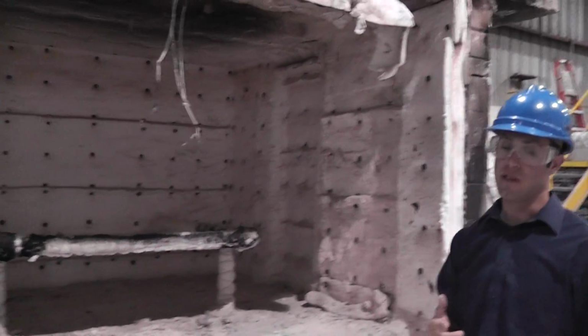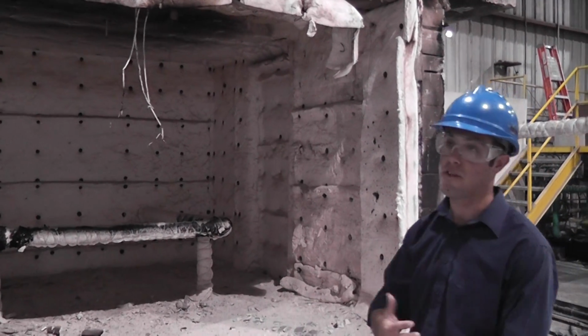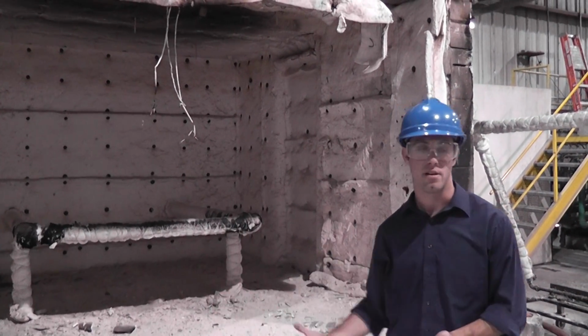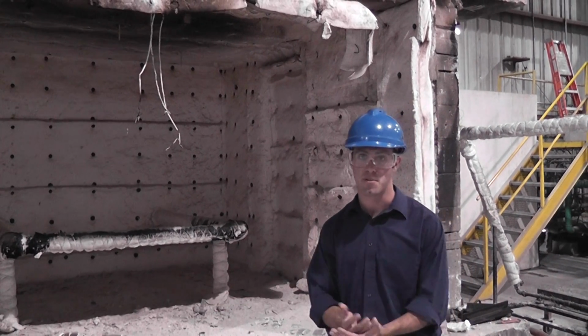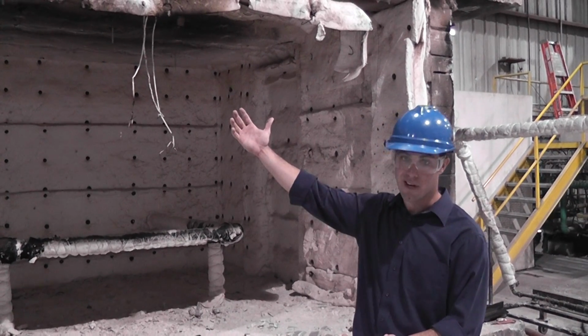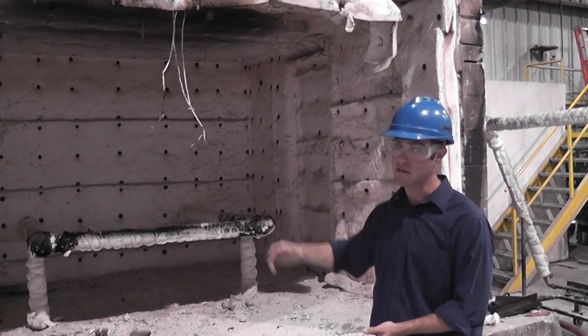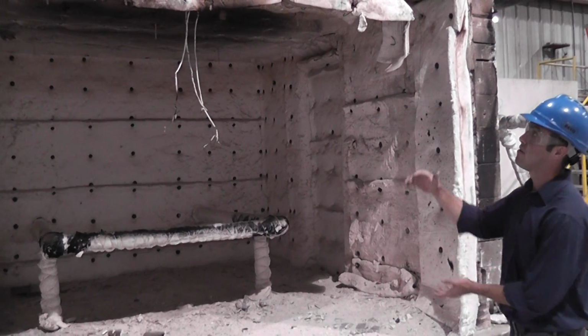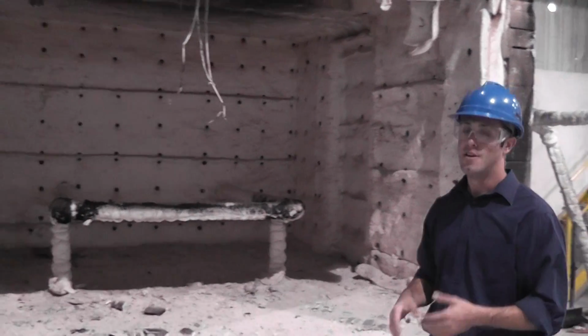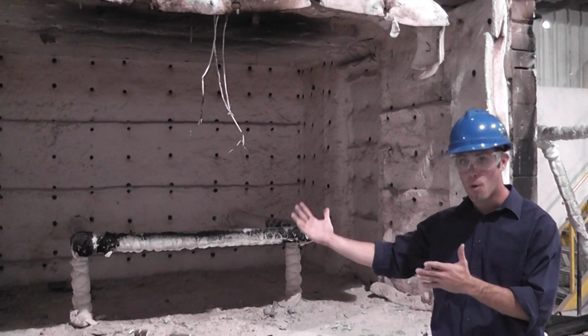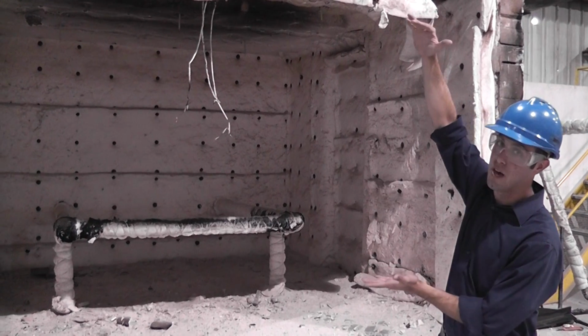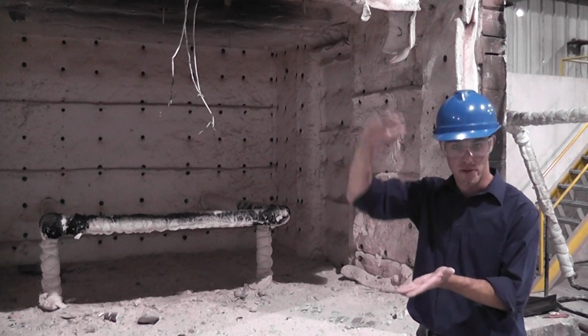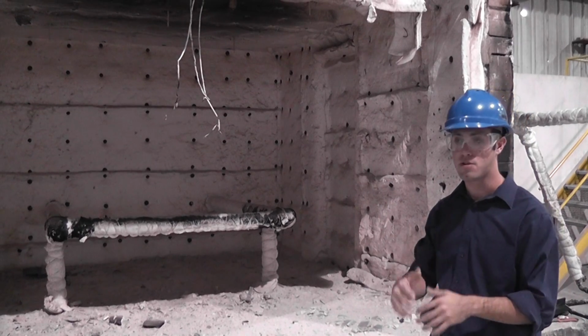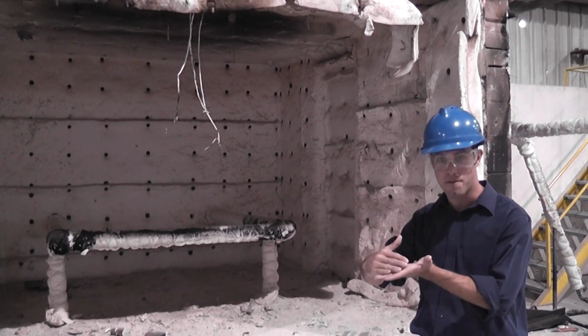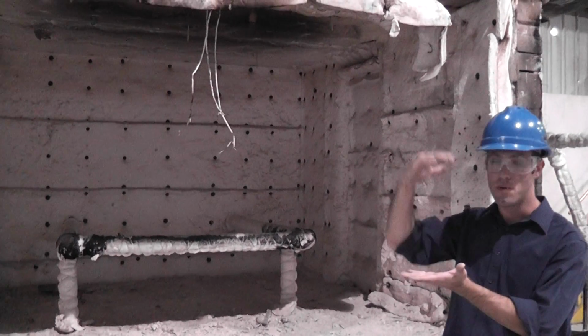So that's 5 minutes into the test. That condition continues for another 25 minutes in the test, and every 5 minutes we up the gas flow based on predetermined calibration rates. We're supposed to hit specific temperatures on the outside of the wall and specific heat fluxes on the outside of the wall. And basically the failure criteria is if flame is able to propagate over the exterior surface or through the core of the assembly 10 feet up above that window, or what would be 1 story in an actual building. We're looking to compartmentalize the fire and prevent it from spreading from one area on fire to another.